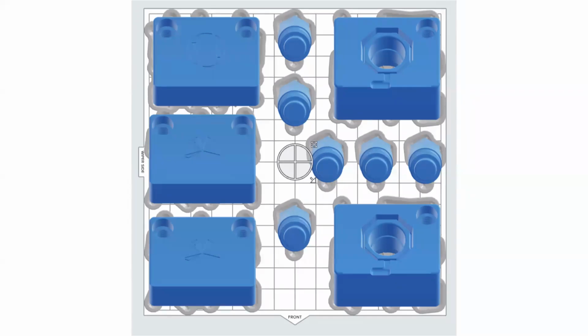Yep. One of the things that we were considering as we were approaching this, I want to call attention to 2 main groups on the screen here. The large square blocks would be our cavities, and in plan view, we're looking at the cylindrical thread cores tipped on an angle. So let's talk about those thread cores first. When we were working through the Rigid 10K setups, we were talking with Formlabs techs about the best possible way to get a truly round core in a robust setup. When they looked at this print orientation, they quickly recommended don't print the cores tilted on this angle, but rather adhere the cores directly to the print bed and do them in an upright cylindrical fashion. Then we closely inspected them at the end of printing to see what we would get. The roundness condition was extremely better. That was an excellent piece of advice from them.